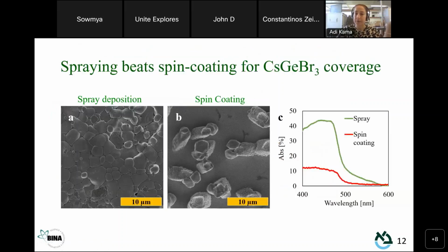So at first we tried to compare the deposition of the same solution, sprayed and spin coated. For the sprayed film, we see more or less good coverage. Particles are connected to each other. When we look at the spin coated film, we see particles that are disconnected from each other. We see more or less just the substrate. And if we look also at the absorption spectrum of those two films, we see a much higher intensity for the sprayed solution and a very low intensity for the spin coated, due to the poor coverage.